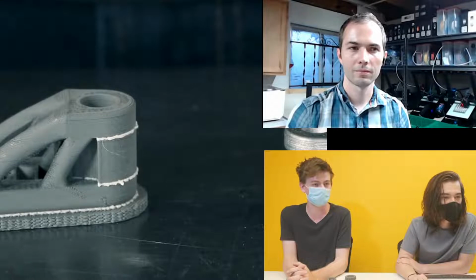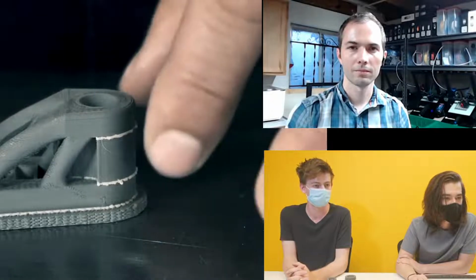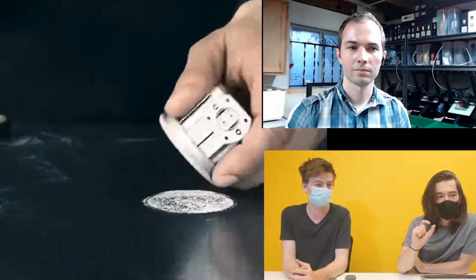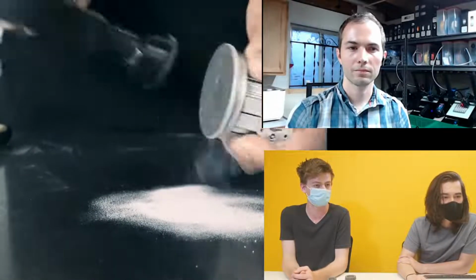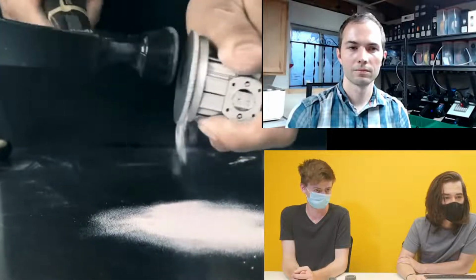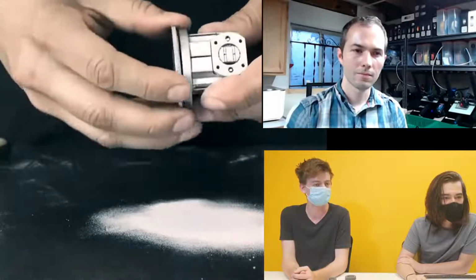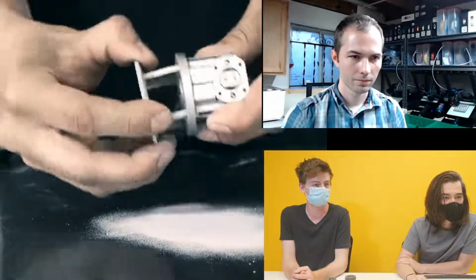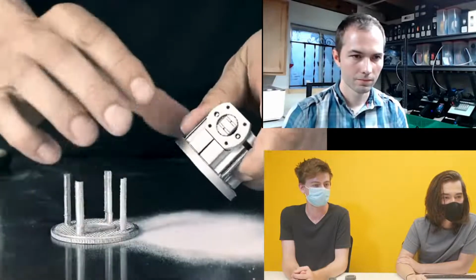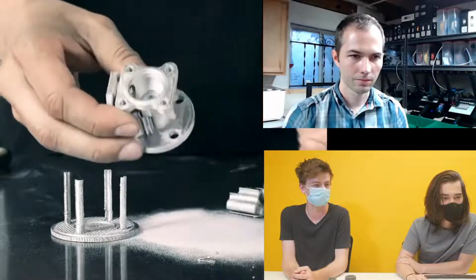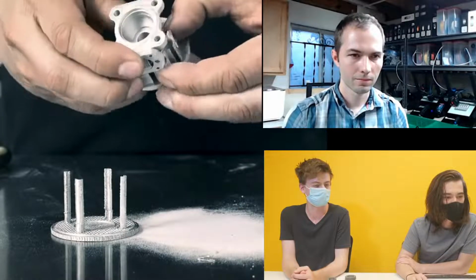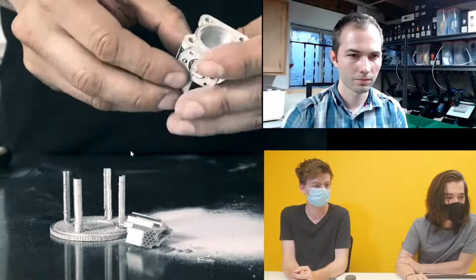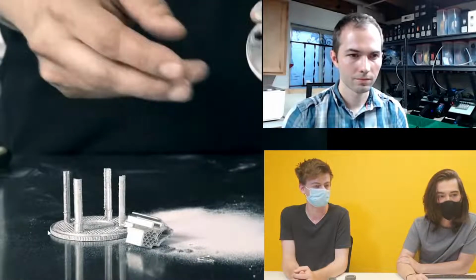It's ceramic supports. You can see the white. It's just the interface layer, interestingly. Well, I think that's how we would have to do it too. Oh, you can't use the polycast itself as support? Because it needs to still be there. And here's what happens, right? You end up with a lot of ceramic powder that you have to clean up afterwards, and you still need to use tools to get the supports out. Whereas this stuff literally becomes ash, and so you're not going to have to deal with this post-processing mess.